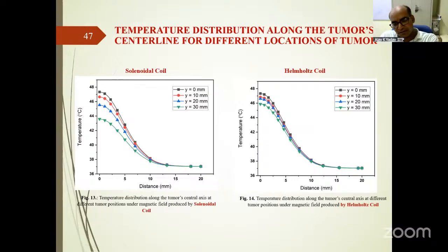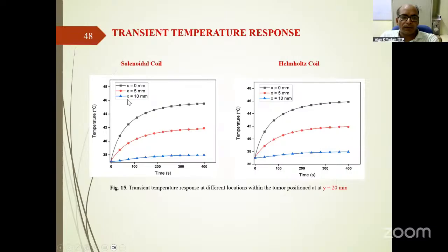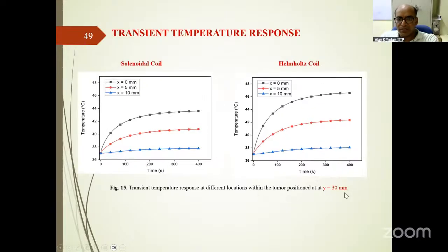It means that the magnetic field is more uniform in this. Here this is for Y equal to 20 mm, 20 mm from the center of the tumor, above or below, it will be the same. So at 20 mm, both the solenoidal coil and Helmholtz coil are giving almost 46 degrees Celsius temperature. Okay, a little bit higher in the case of the Helmholtz coil. But if you go to Y equal to 30 mm, you can see the Helmholtz coil is still giving very high, around 46 or above, and this one has dropped to 43 or 44 in that range. So this is the difference.